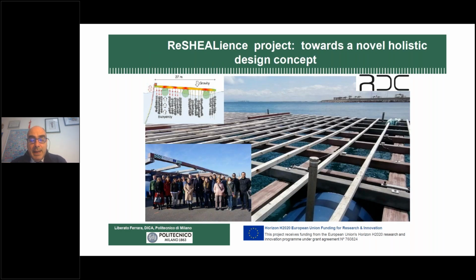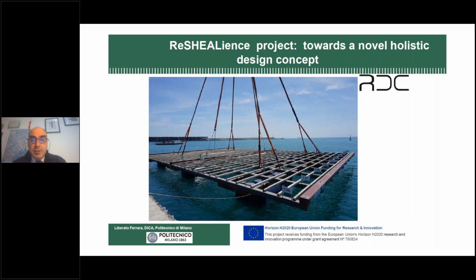This is the pilot in the Galway Harbor, a raft for mussel farming. It's floating, and we also have a camera streaming 24 hours live, so we can inspect the prototype at any time, and periodically we go to it to inspect the cracks and the healing. Some of the beams this prototype consists of were pre-cracked. There were different levels of pre-stressing to check the efficiency of the material in different conditions. And this is an image of when the pilot was floated in May 2020.